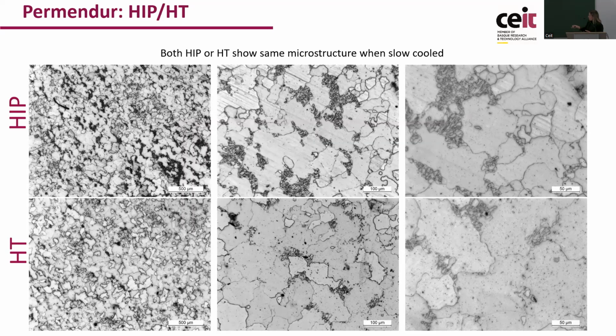Another thing that I wanted to say is that both in hot isostatic pressing and conventional heat treatment, if we do the same thermal cycle with a slow cooling, the obtained microstructure and properties are the same. So from now on, we were just focused on the conventional heat treatments. Also because as the material from SLM was already quite dense, there was no need for closing porosity by hot isostatic pressing.